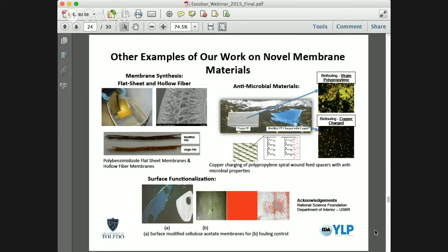Then just to finish, I'm getting close to my last slide, showing you a little bit more of what my group does. We work a lot with layer-by-layer activation of surfaces of polybenzimidazoles, in both flat sheet as well as hollow fibers, and we give them more hydrophilicity, we give them charge. We functionalize them. When there are pores, we functionalize the pores. We make a lot of antimicrobial surfaces by charging membranes and charging feed spacers with copper and by chelating them in a way that they are not separated, so that separating them from other surfaces is very difficult. And we see significant decreases from an unmodified biofouling to a modified surface biofouling.